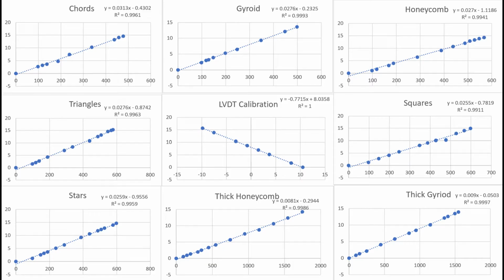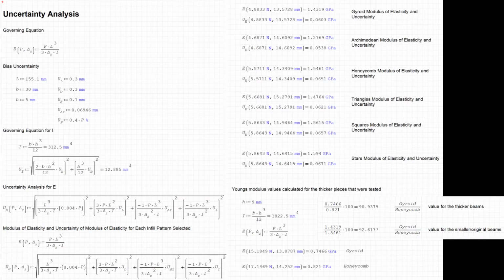The goodness of fit for each set of calculations is represented by the R-squared value on each graph of mass versus deflection. All of these R-squared values are above 0.99, meaning that it is a very good fit. The theoretical uncertainty and the empirical uncertainty values have been discussed and are also shown on the Mathcad uncertainty analysis. We concluded that our observed uncertainty values are similar to what our predicted values were because our uncertainty was almost negligible. Both the empirical and the theoretical uncertainties are agreeable.